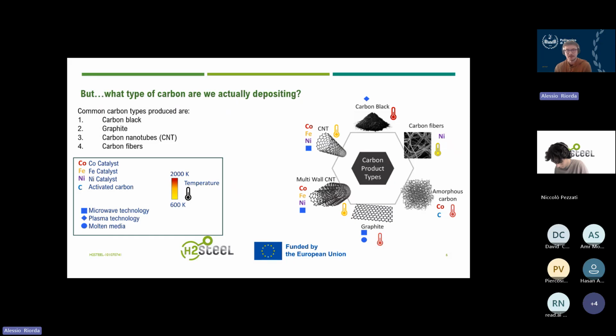But which kind of carbon are we depositing? It strongly depends on the characteristics of the process. So it depends on whether you're working with a thermal process or with a catalyst, and which kind of catalyst. For example, we have different kinds of carbon, like carbon black, just really small particles of carbon, or carbon nanotubes. These tubes of carbon are generated normally with metal catalysts, because we have the deposition of the carbon on the catalyst and then the migration of the carbon inside the catalyst and then deposition at the end, at the contact with the support, that generates these beautiful carbon nanotubes or fibers. And also the temperature is helping the generation of one of these types of carbon deposited.